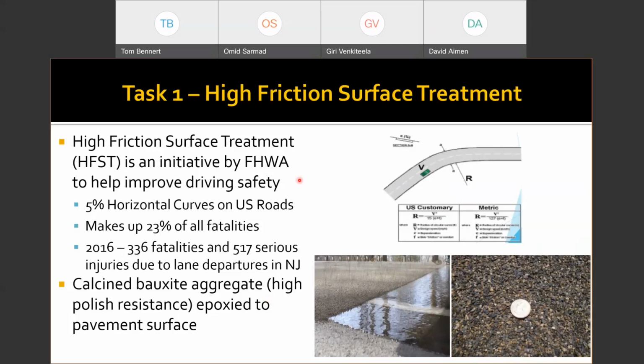And really just to simplify it as best as I possibly can, what we're doing is taking a very hard angular stone, which is this calcined bauxite, and gluing it to the pavement. You can see in the picture on the left that this is an epoxy resin applied evenly across the pavement surface. Right now, you're seeing a picture from underneath the system where the calcined bauxite is being dropped down onto the epoxy. That's allowed to sit and set up for a little while until the epoxy hardens. Then the loose material is brushed and swept off, and your final product looks like the picture on the right.